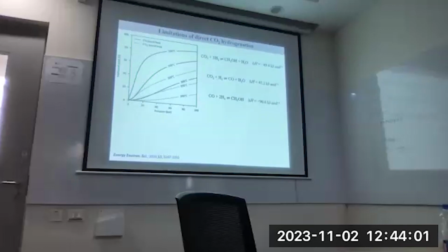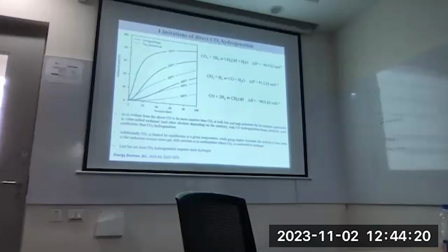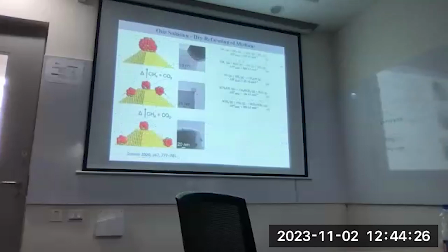But in the case of carbon monoxide, if you want to get methane from carbon monoxide, you can get more of it at just 200 degrees Celsius, more exothermic, and you can easily convert all of the carbon monoxide. In my project, first at Breathe Applied Sciences, we used to do this process, which is not very efficient. When I went to KAUST, we moved to another process called DRM, dry reforming of methane, an indirect way of hydrogenating to methanol.